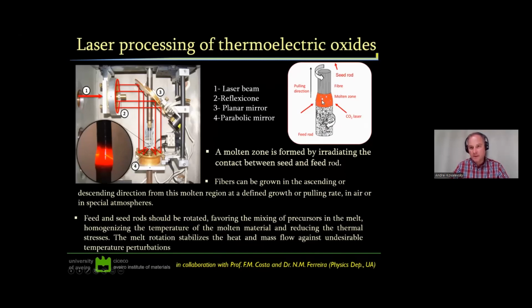So we melt the contact between seed and feed rod, and then we can grow the fiber made of our thermoelectric materials, either up or down. And we also can rotate the feed and seed rods to improve the homogeneity of the melt.